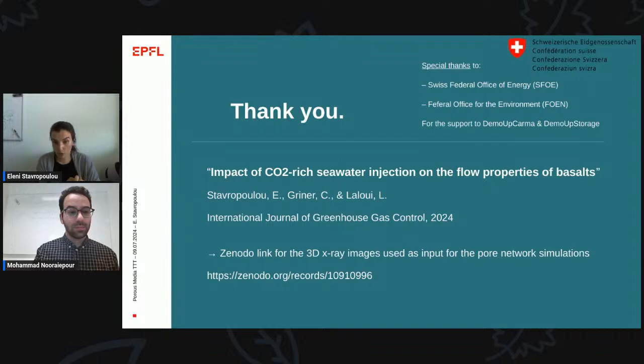Now, in terms of dissolution that you mentioned, usually dissolution is what happens first, and then we have eventual precipitation. In the cores where we saw reduction of flow, we only have the scan after the reduction, so we cannot have an image of when the dissolution might have occurred. We have directly the end. We were not able to have quantitative measurements of the changes of the porosity.